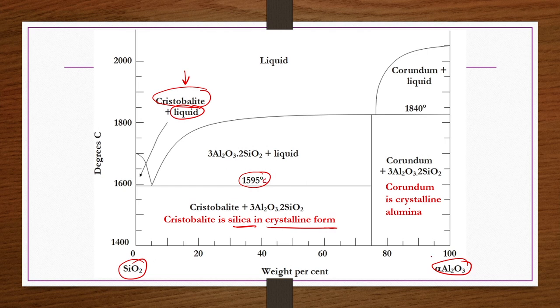And then if you have almost pure alumina, with only 20-25% of silica present, then you can have a liquid sample plus corundum, which is nothing but crystalline alumina. This corundum is the crystalline alumina at temperatures of more than 1840 degrees centigrade, right.